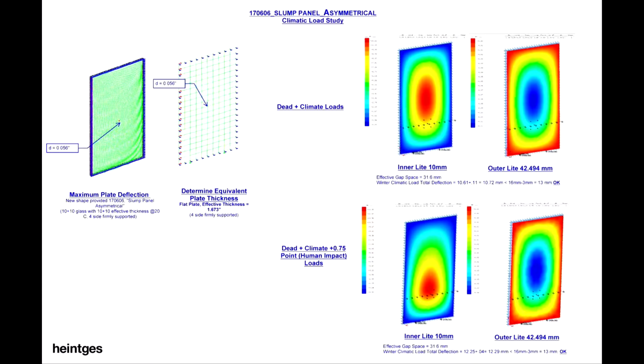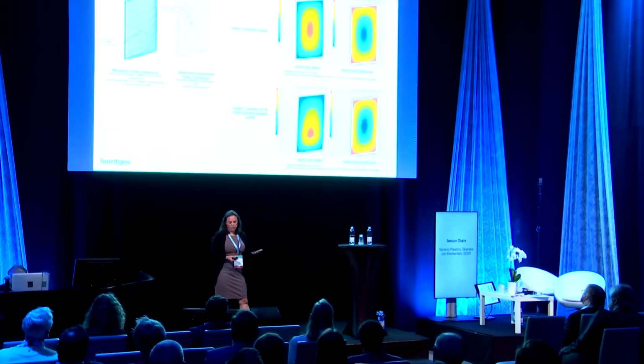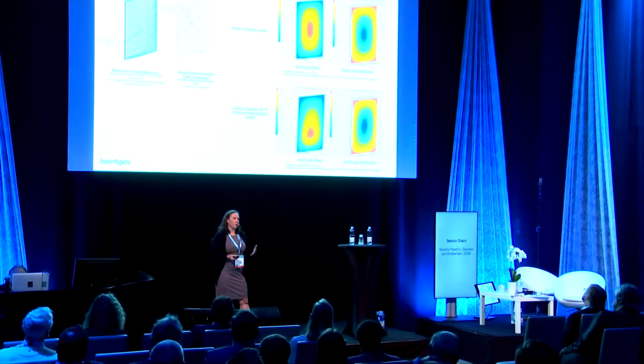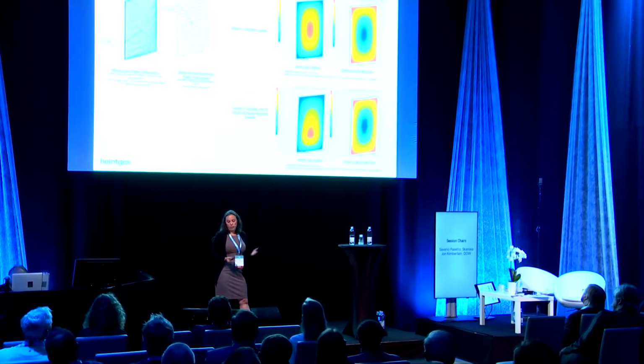Approximately 1.5 inches equivalent of glass was used to check the deflection under climatic loads of the inner light, which being much thinner would do most of the deflection. We wanted to make sure that the stress on the edge seal was okay, and also that the two lights wouldn't touch under any of the expected conditions, including when you incorporate in all the glass tolerances.